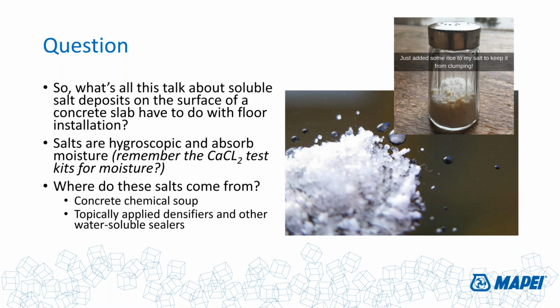Well, the same thing that we talked about with the salt shaker and a calcium chloride test is happening on top of a concrete slab because of this soluble salt soup that's on the surface. It can come from excess bleed water, it can come from too much water in the mix, it can come from topically applied densifiers and other soluble materials that can add to the overall salt concentration on the top of the concrete slab.